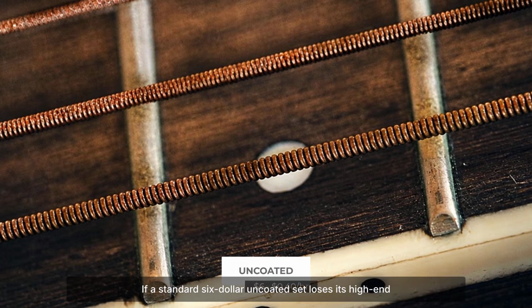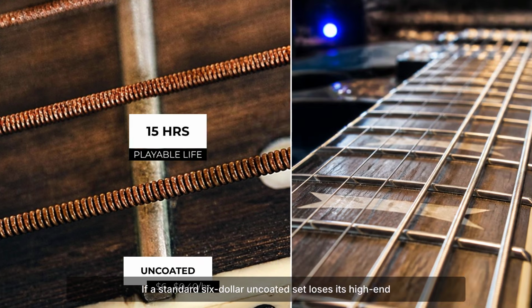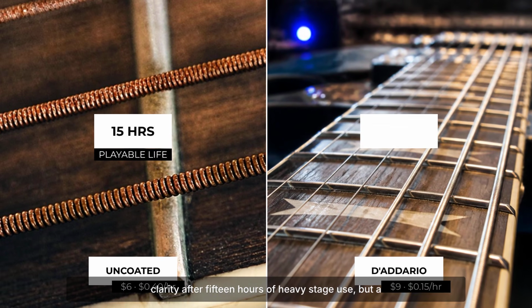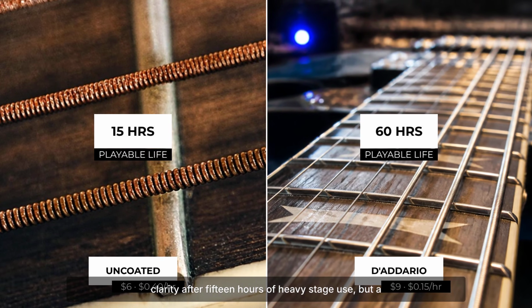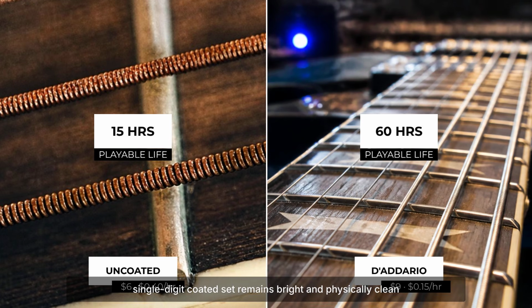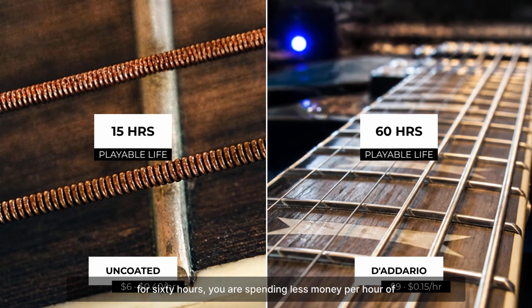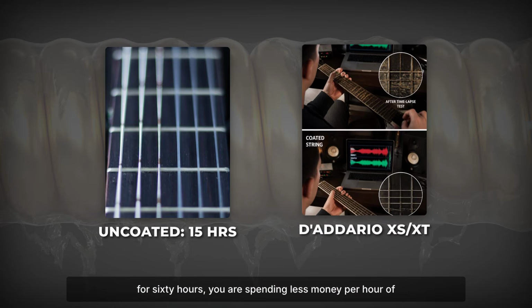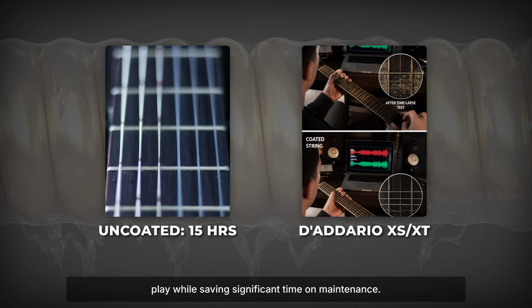If a standard $6 uncoated set loses its high-end clarity after 15 hours of heavy stage use, but a single-digit coated set remains bright and physically clean for 60 hours, you are spending less money per hour of play while saving significant time on maintenance.